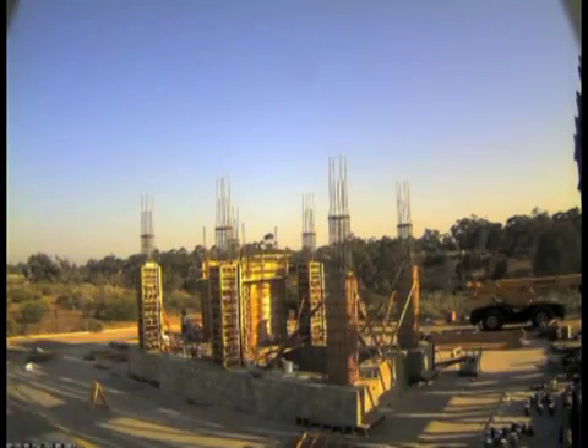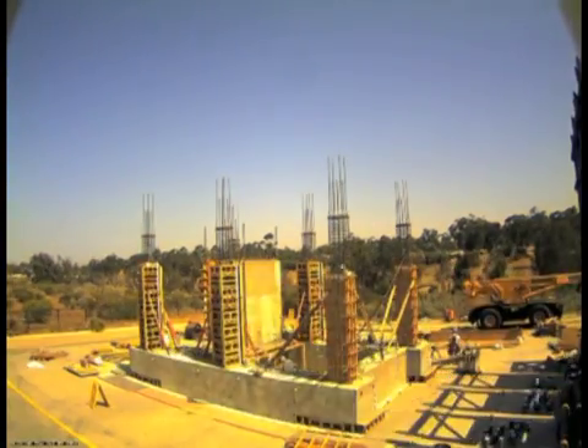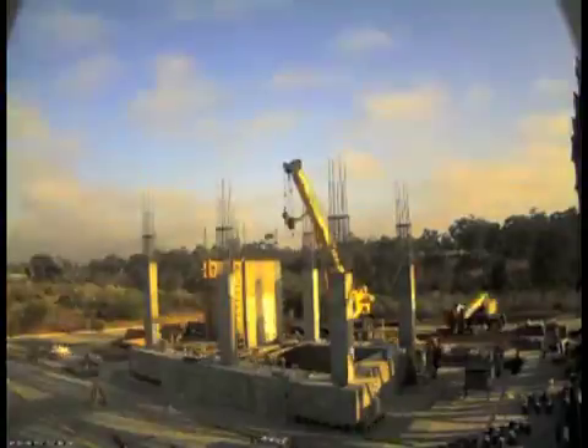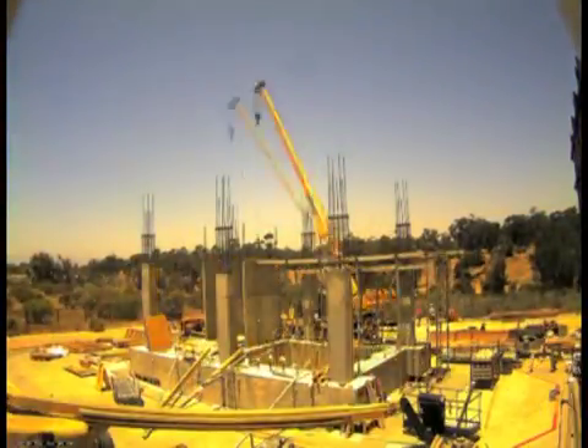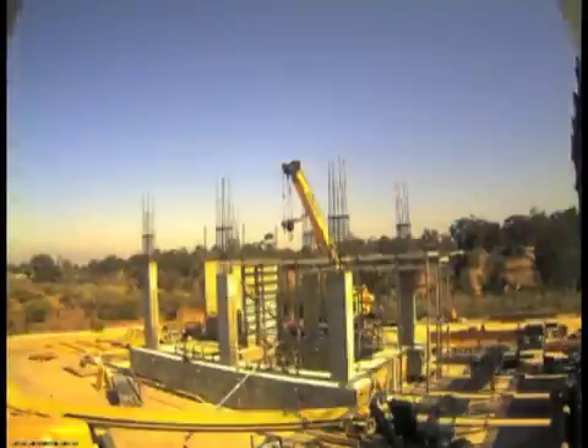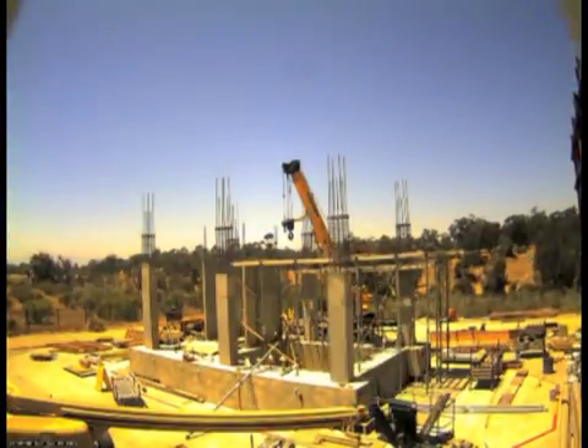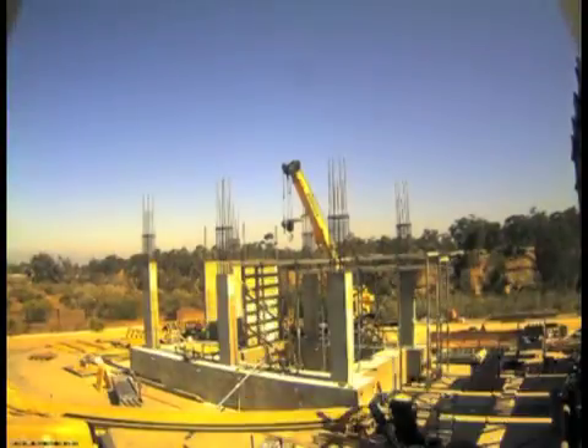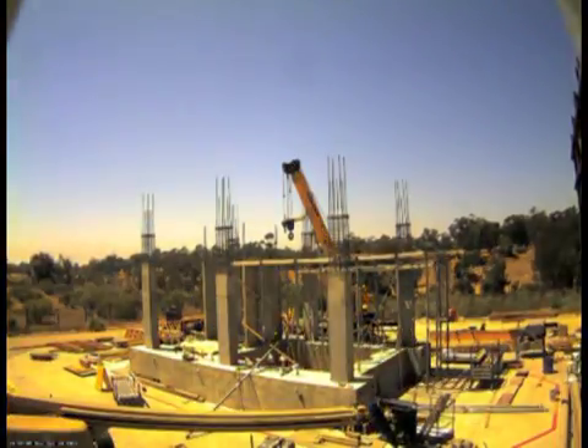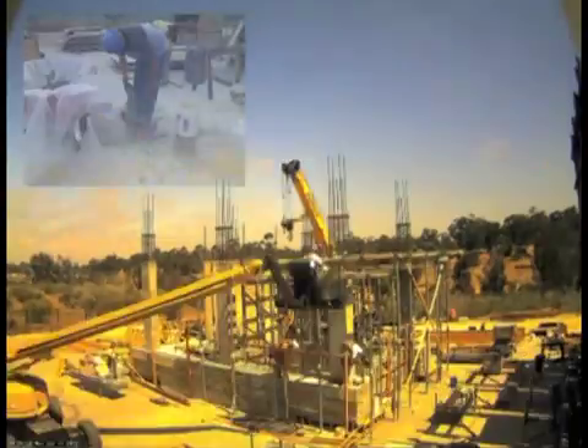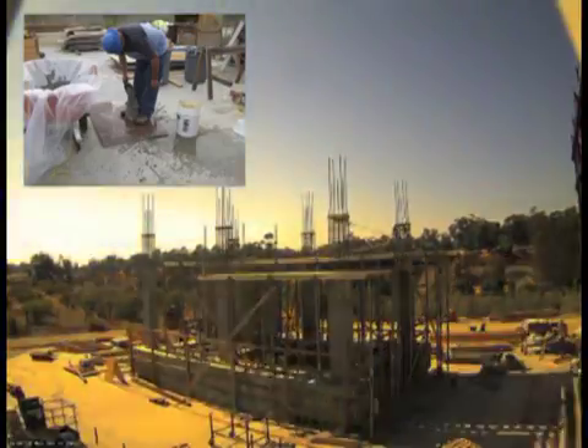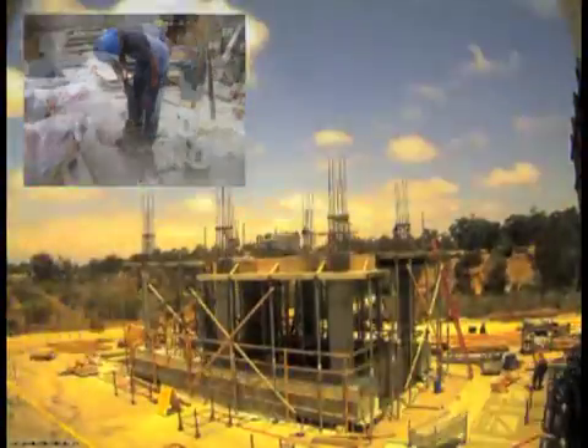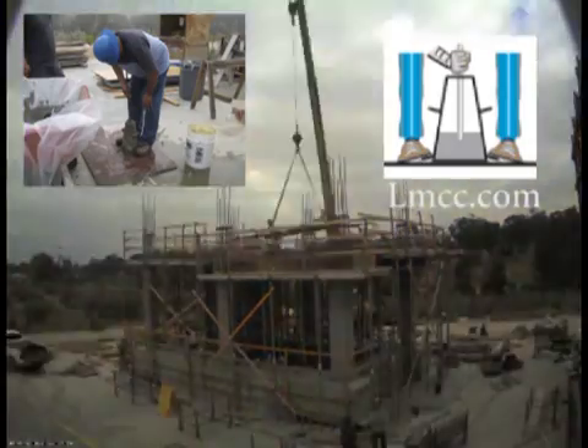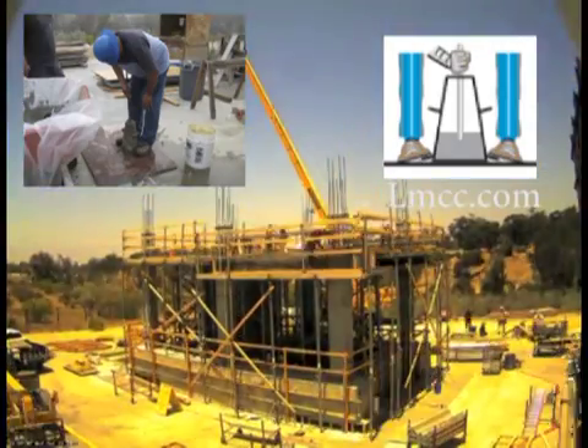Falsework can consist of beam clamps, braced frames, timber scaffold tubes, and props. Every time concrete is poured during a construction job, several standard tests are conducted to verify the expected workability and strength of the concrete mix that is delivered to the site. For each concrete truck that arrives on site, a slump test is performed immediately on the side of the job site. A cone-shaped mould is first filled with wet concrete. Then a metal rod is inserted into the top of the cone and pumped up and down 25 times. This helps eliminate air bubbles and increases the homogeneity of the concrete mix.